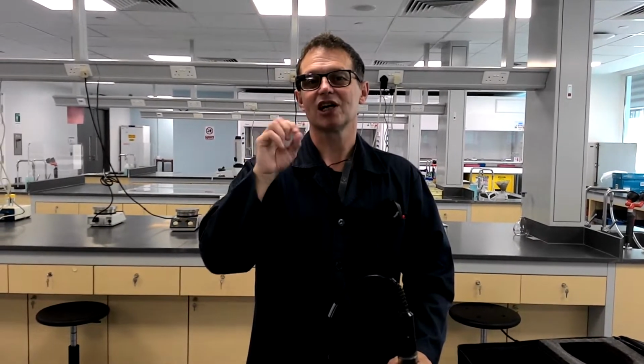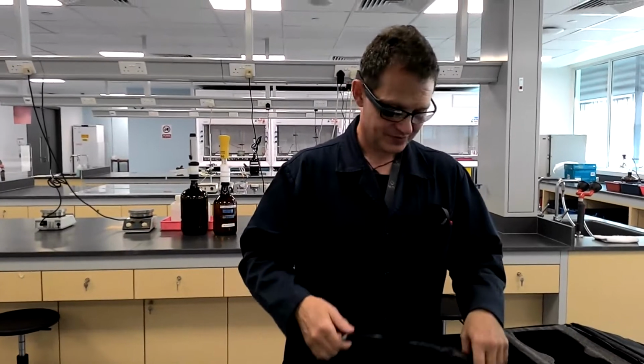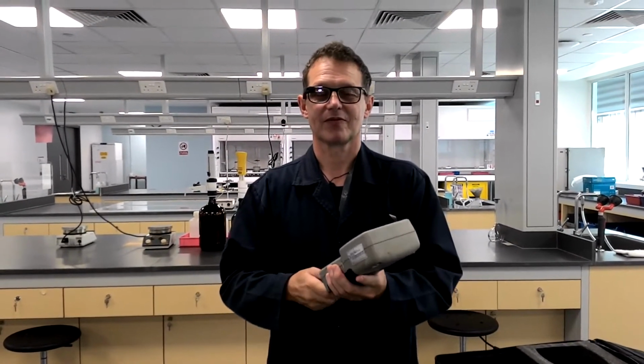Secondly, the glass itself, without being complicated, it's not just any old glass that you use for your window that you make a pH probe out of. It's quite a careful glass with careful permeability. When you get crystals forming on the glass, you can actually disrupt the surface of the glass, which again, even if your reference electrode is working, will damage the glass and therefore compromise the reading that you're taking. Wow. So, storage is certainly more convenient, but a good deal more destructive. I see. I'm thinking that could there be some rusting of the electrode, because now there's no liquid and air, the oxygen there could do some oxidation there?